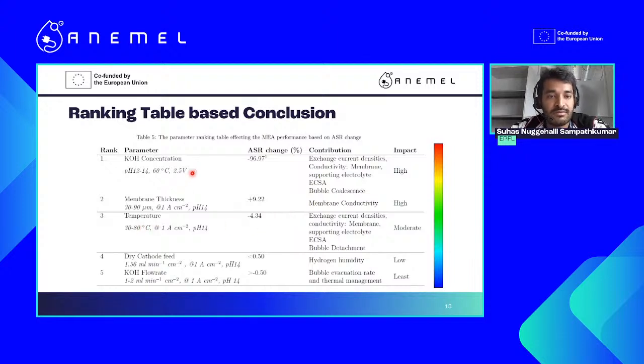For instance, for KOH concentration, we did not reach 1 ampere per centimeter square, but we see that based on the model, between pH 12 to 14, KOH has the highest effect, followed by the membrane thickness, temperature, dry cathode feed, and then the KOH flow rate. So this kind of gives us an operating profile to worry about, to research on, to know that the model predicts quite well what could be the effect of these concentrations.